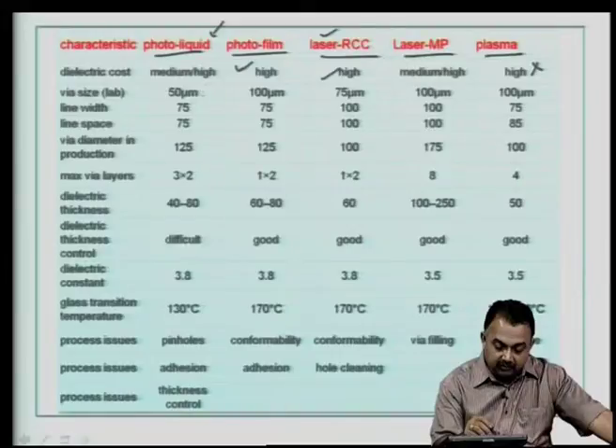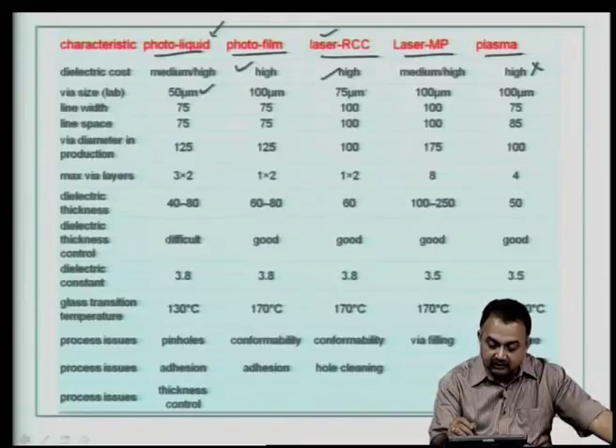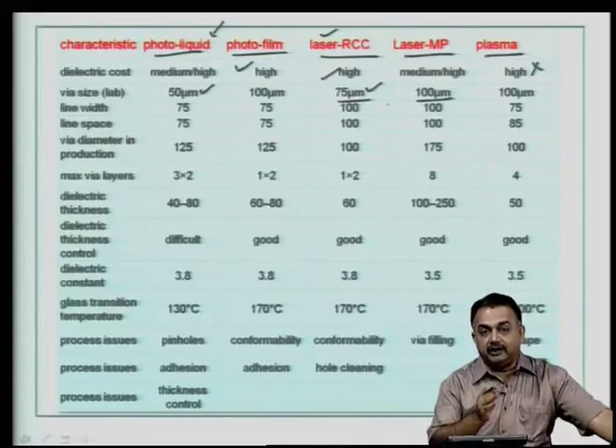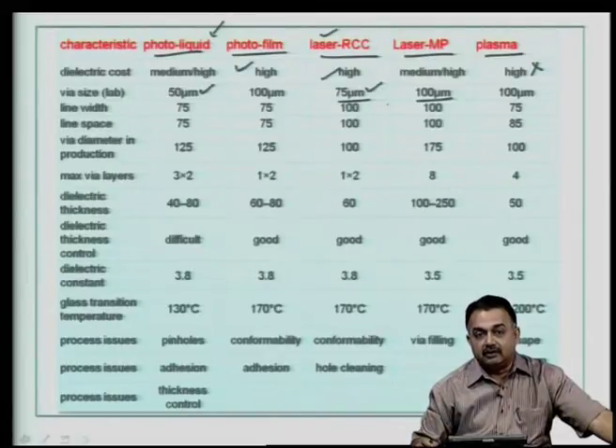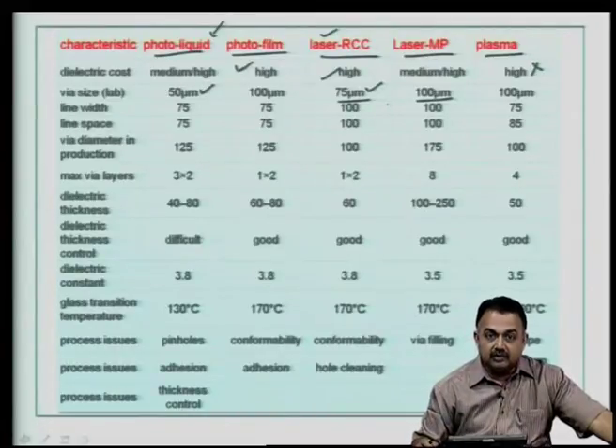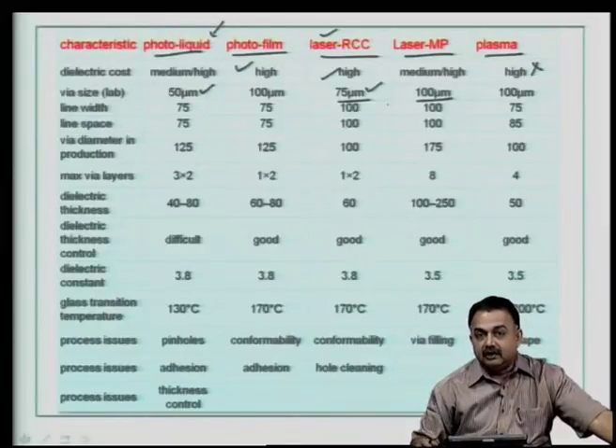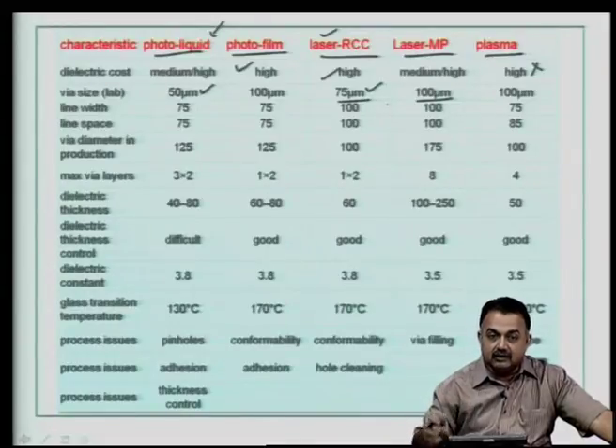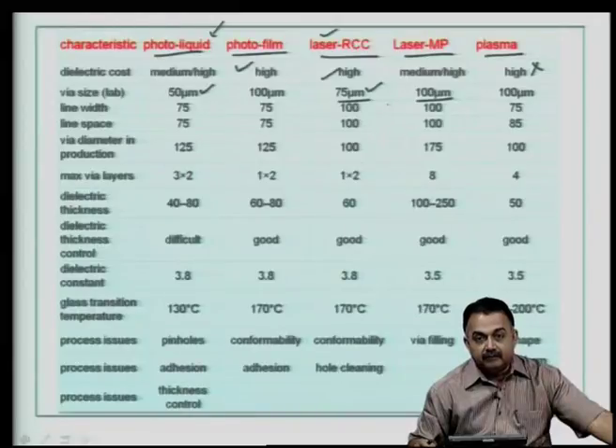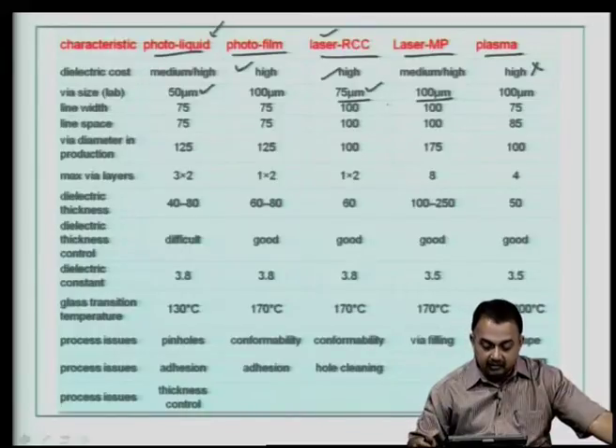Typically liquid photopolymer you can work from 50 microns. Current day technologies for laser also targets 50 microns, but very safe is 75 to 100. So, typically the range from 50 to 100 should be possible for various methodologies listed here to create a microvia. And as I said, by definition a microvia is one which falls in the range of less than 125 microns, around that number, because otherwise it can be done by a mechanical drill and does not classify as a microvia.